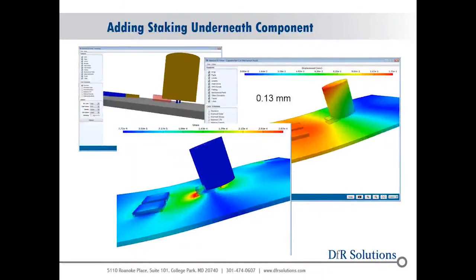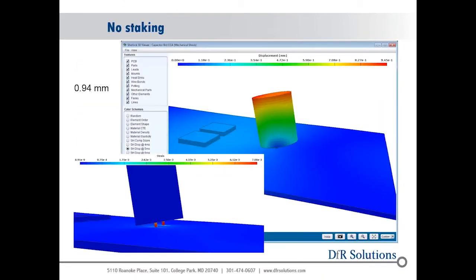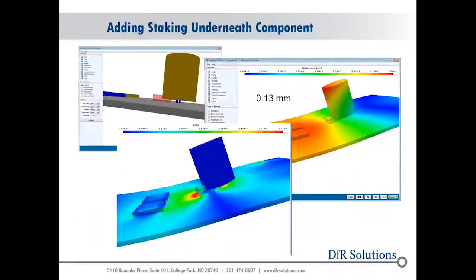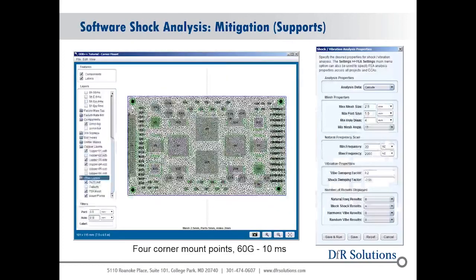Without the staking added, I can go from about a 0.9 millimeter deflection during the shock event. By just adding a little bit of staking to one side, I can actually cut that down to a tenth. So where it would fail without staking, it will pass with the staking. So that's just an example of how it can show the effect of staking. When somebody asks, well, do I need to, it's an added assembly step. People want to know if it's necessary to prevent a failure. And with this, you can actually show them, yes, I can put staking and prevent the failure.